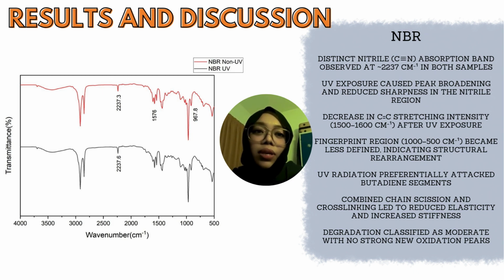Furthermore, the fingerprint region between 1000 and 500 inverse centimeters became less defined after UV exposure, indicating structural rearrangement within the polymer matrix. The absence of strong new oxidation peaks suggests that the degradation was moderate and had not progressed to severe oxidation under the experimental conditions.